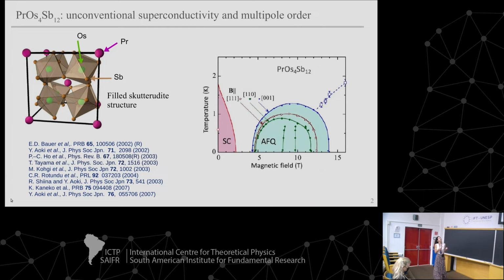So this material was discovered quite a long time ago. At least it's been known for a while, but the phase diagram was investigated and superconductivity was discovered in 2002, which is what brought some attention to it. So the crystal structure is here. It's a filled skutterudite structure. So the praseodymium atoms sit on the corners of this cubic structure. It's slightly distorted from cubic, so these cages here of the antimony atoms are slightly distorted, which gives it a tetrahedral rather than a pure cubic symmetry. And this gives you a little bit of anisotropy in the phase diagram.